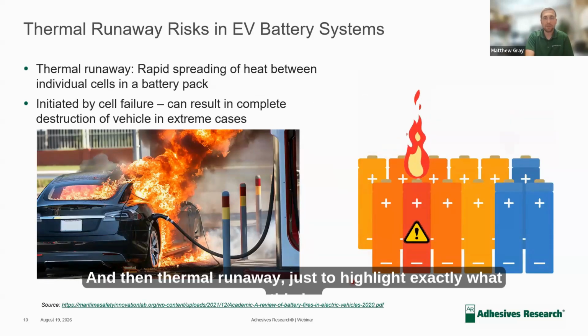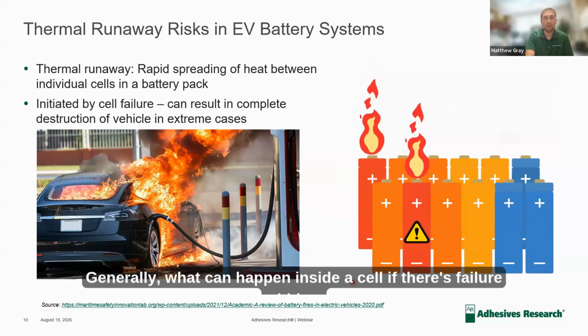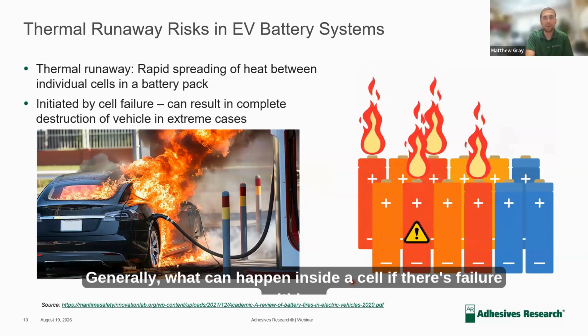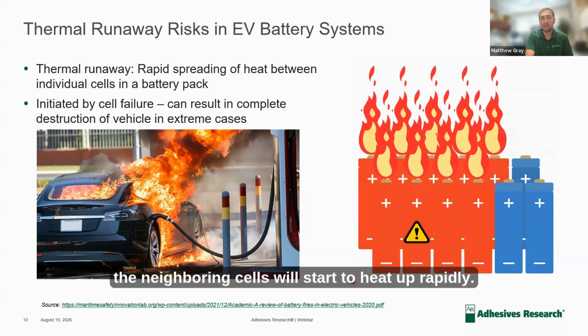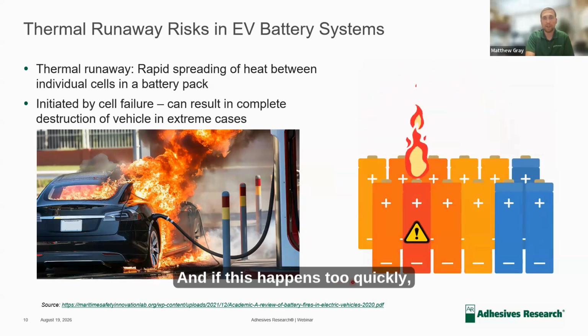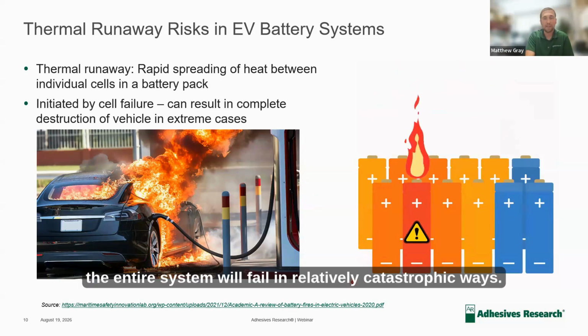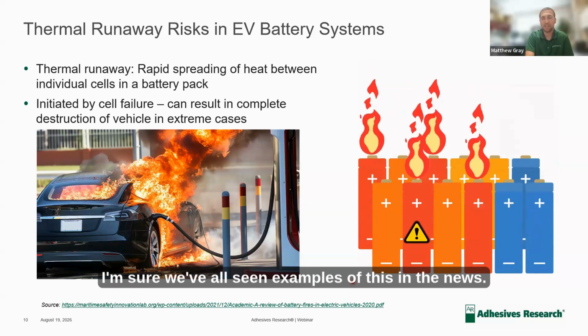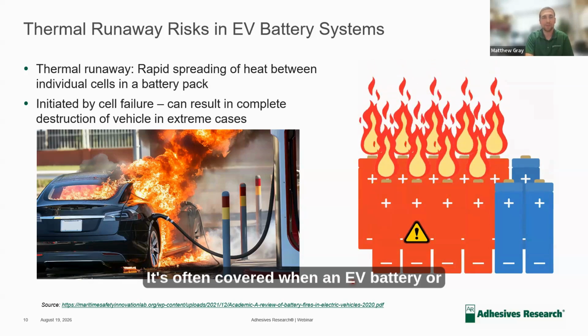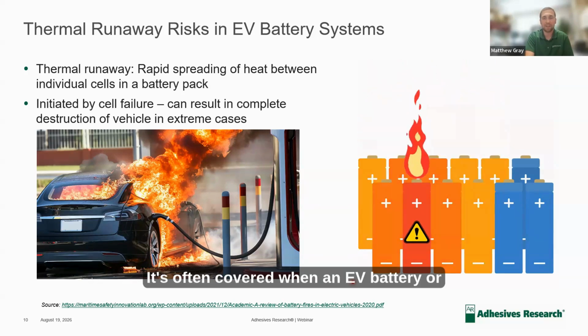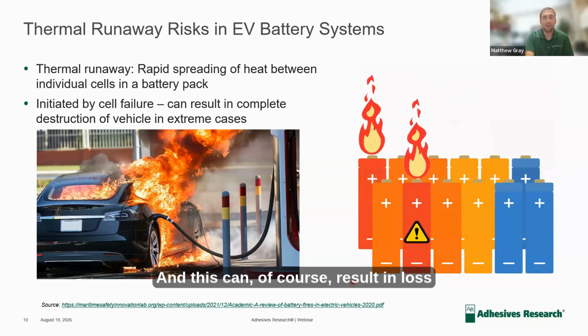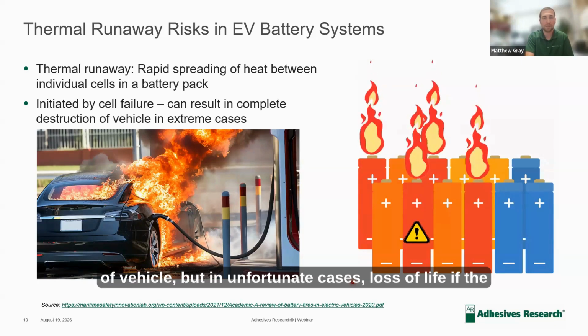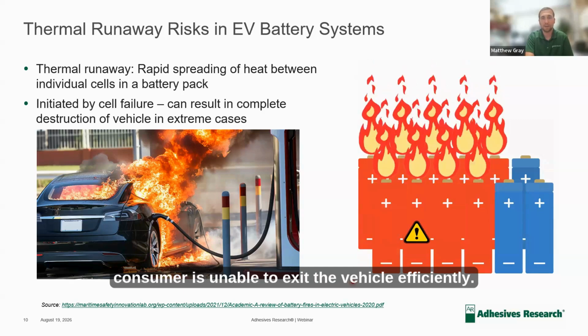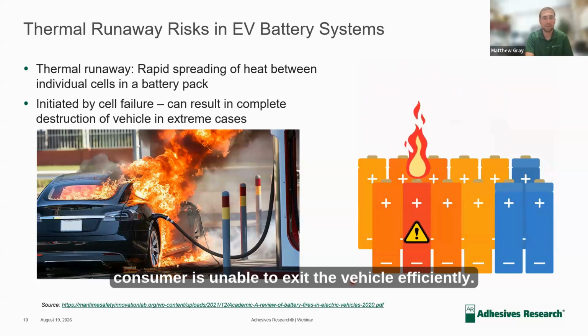And then thermal runaway, just to highlight exactly what this is. Generally, what can happen inside a cell if there's failure within a single battery cell is the neighboring cells will start to heat up rapidly. And if this happens too quickly, the entire system will fail in relatively catastrophic ways. I'm sure we've all seen examples of this in the news. It's often covered when an EV battery or an EV vehicle goes off. And this can, of course, result in loss of the vehicle, but in unfortunate cases, loss of life if the consumer is unable to exit the vehicle efficiently.